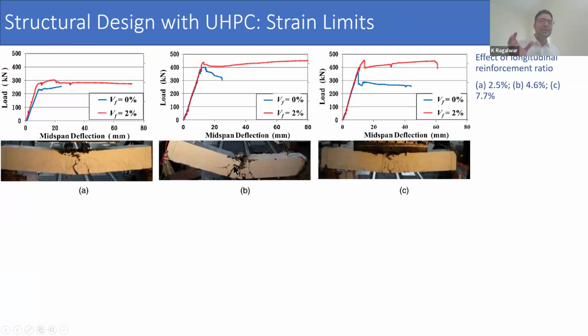It is important to understand why this localization strain is important. So these are the three different tests carried out on the longitudinal reinforcement effect. You see that stress localization happens in all the different beams, but that leads to very different behavior under flexure based on the reinforcement. So the amount of reinforcement placed also dictates how the behavior changes and how localization is detected. But it is a varied behavior. It is very difficult to cap.